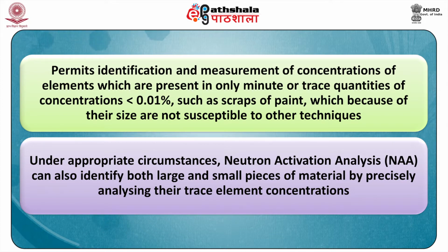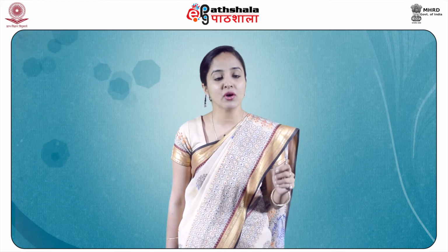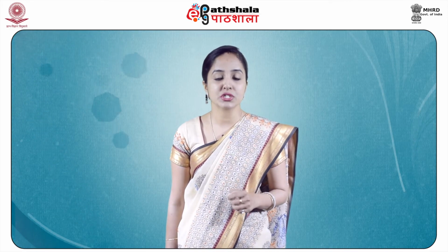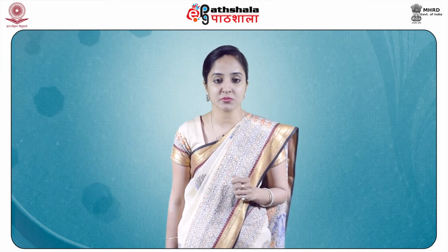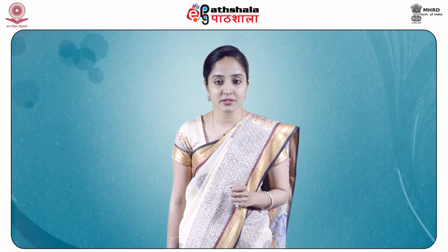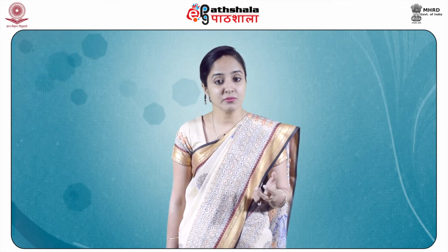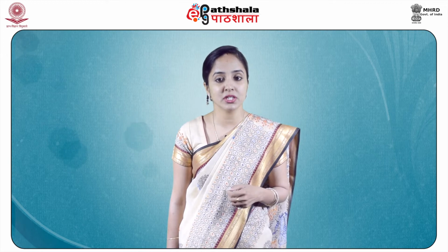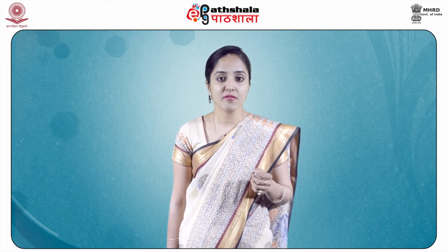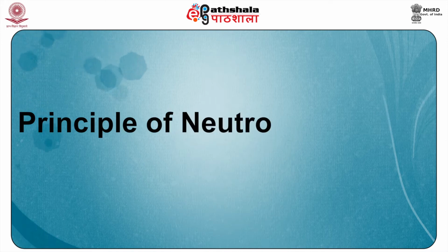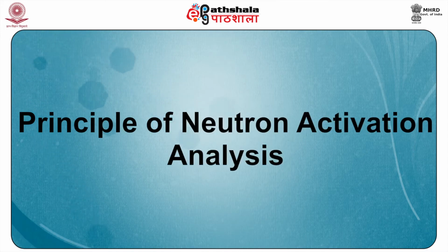Under appropriate circumstances, NAA can also identify both large and small pieces of material by precisely analyzing their trace element concentrations. Such identifications rely on the fact that although concentrations of the major constituents of similar specimens, such as two pieces of glass, may be nearly the same, sometimes trace elements as impurity show a wide variation from one source to another. Now, what is the underlying principle of neutron activation analysis? Let us focus our attention on that, students.